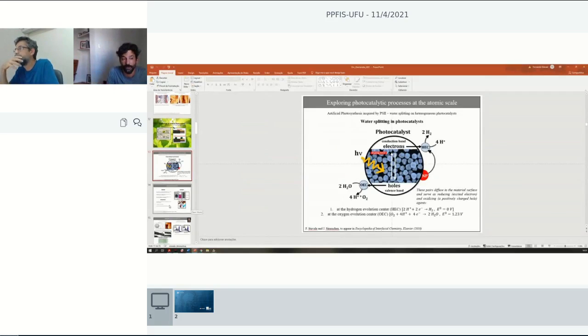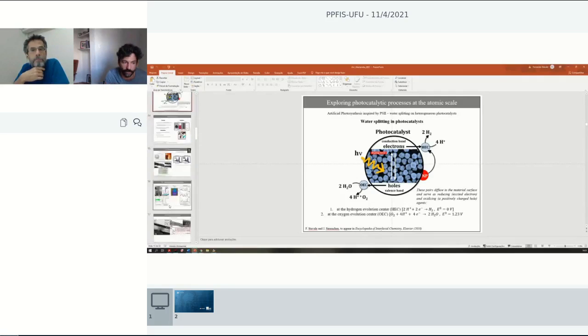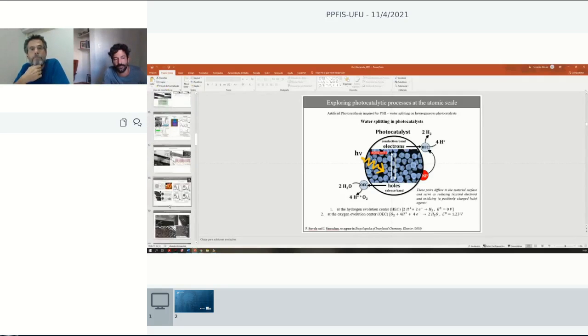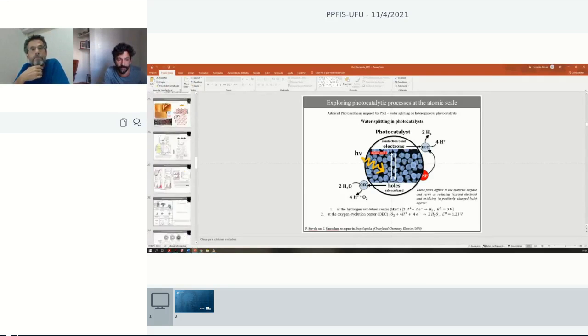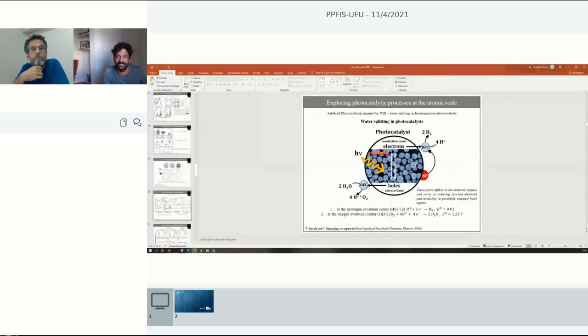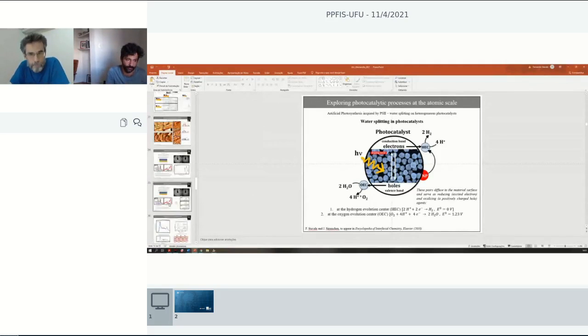Sure. Right. But one thing that is still missing, for instance, in the study that I have shown you about the cobalt doping, is that there is a chance that some amount of the dopant that I expected to be doping the oxide could be segregated to the surface. To settle this debate, I need to do the STM image of the doped system, something that I have not shown you because we have not done it so far. But from the spectroscopy measurements, I don't see any evidence of a cobalt metal nanoparticle, because it would have a very clear signature from the spectroscopy point of view.